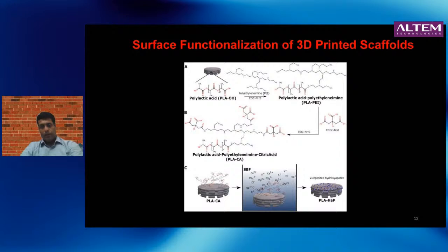So what we did was to take our scaffold and put it in what is known as simulated body fluid, or a supersaturated solution of calcium and phosphate ions, hoping that they would actually deposit on these scaffolds. That really didn't work, because what we found is even after several days of putting it in the solution, nothing was actually getting deposited. So the substrate wasn't great for depositing calcium phosphate on it. So we realized we need to modify that.